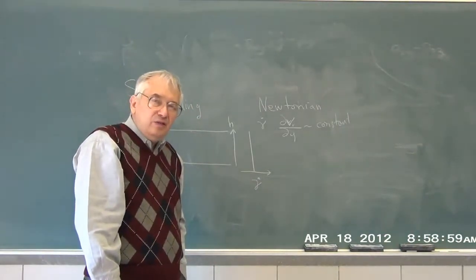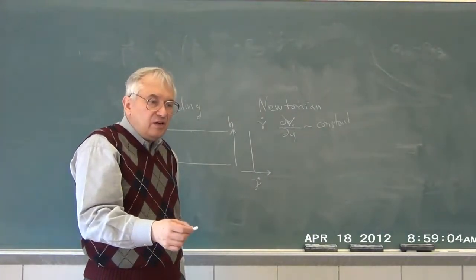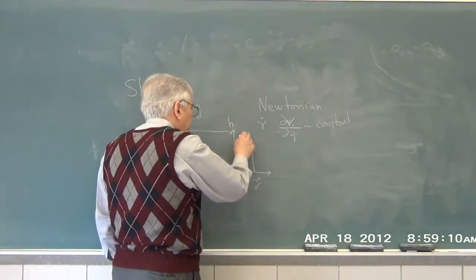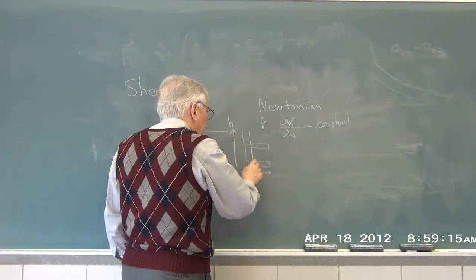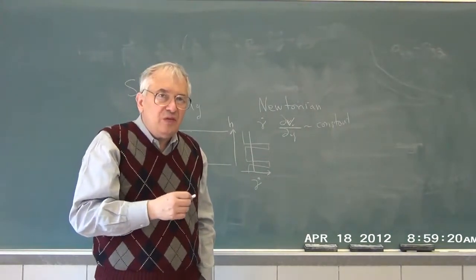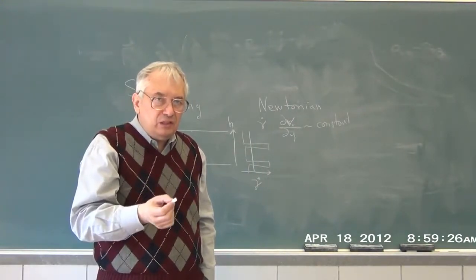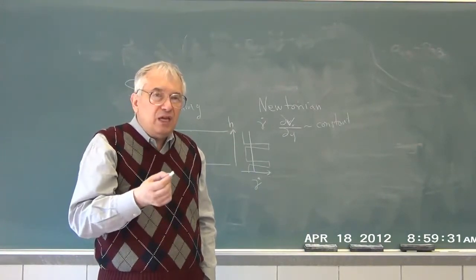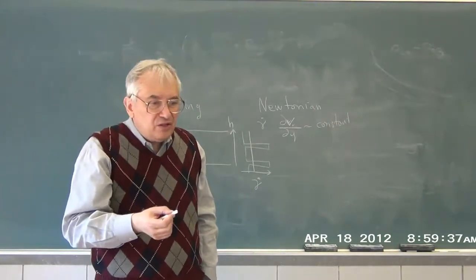However, if you actually do this to real polymer solutions that are adequately concentrated, and do the experiment, what you discover is that the shearing tends to be confined to some fairly narrow bands as opposed to being the same everywhere. It's as though the fluid had formed yield planes and was yielding near those planes. These appear to be equilibrium shear bands in that if you do things for a long time, everything just sits there.